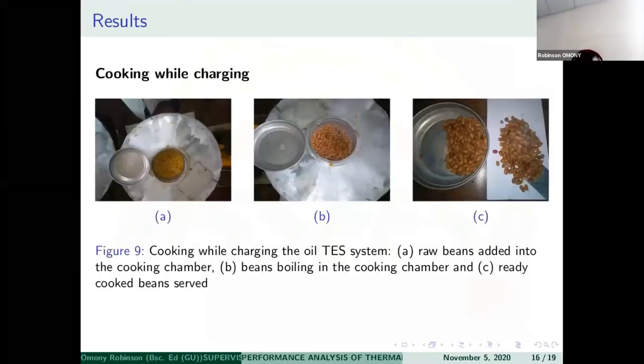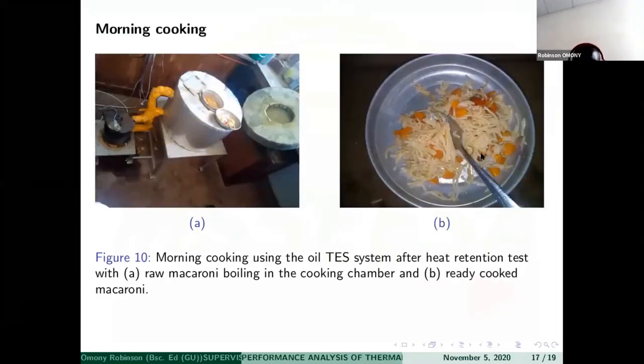Now, these are some of the outcomes of the cooking experiment carried out. A is raw beans added into the cooking chamber. B shows beans boiling. And of course, C is ready served beans. This was an experiment carried out in the morning after heat retention using the oil TES. So after the 14 hours, the temperature inside the storage was still high enough for cooking something that you can prepare like for breakfast.